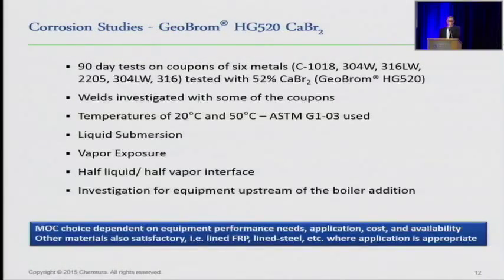We did some corrosion studies, and I presented this data back in Chicago, but I thought it would be helpful to do it again. We've got copies of them out there at the table. If you want to look at them, that's fine. If you'd like to talk to me about them, I can explain some more about what our folks looked at. Basically, we looked at 90-day tests at 20 and 50 degrees Celsius. Some of those coupons had welds. We looked at a carbon steel, different stainless steels, and a duplex alloy with calcium bromide. And then we looked at liquid, vapor, and a mix of liquid and vapor submersion to show if you have issues at the interface of the liquid and the vapor,